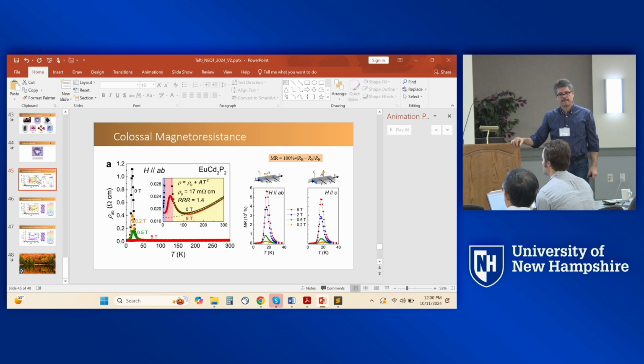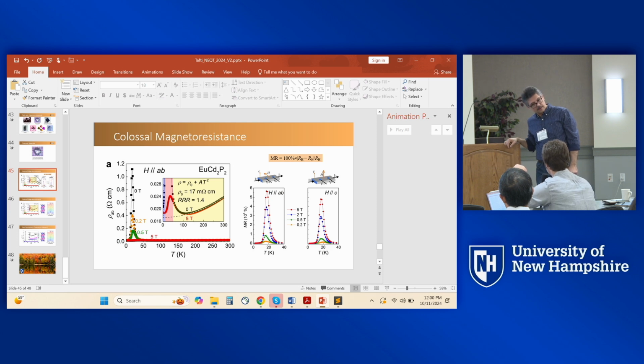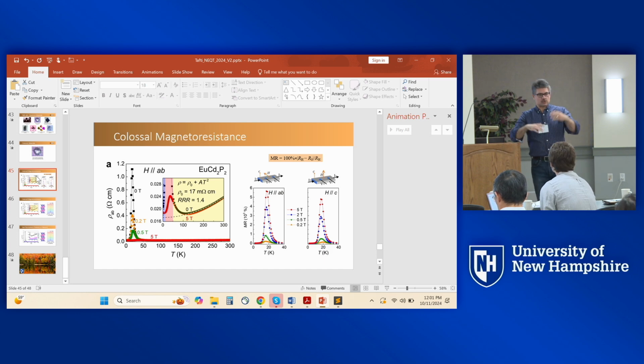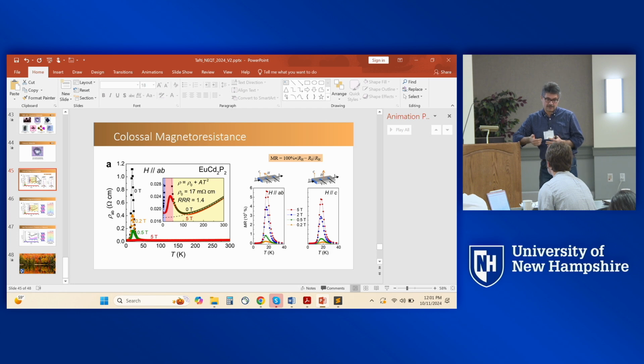Okay. And then my other question is about the phonons. I forget which material showed this anomalous behavior. The germanium, yeah. Do you have any complementary investigations of the lattice? Do you notice any anomalies? No, in fact, that would be a very interesting neutron scattering experiment, and I'm happy to discuss. This is a chiral crystal, so there could be very interesting dispersion of phonons, for example. We only got Raman, and Raman only sees the optical phonons. What we have done is crystallography at high temperature and low temperature, not a thorough temperature dependence. There are no structural transitions, nothing dramatic. But what's interesting in these systems is to access the acoustic phonons, ultimately, which neutrons could do.